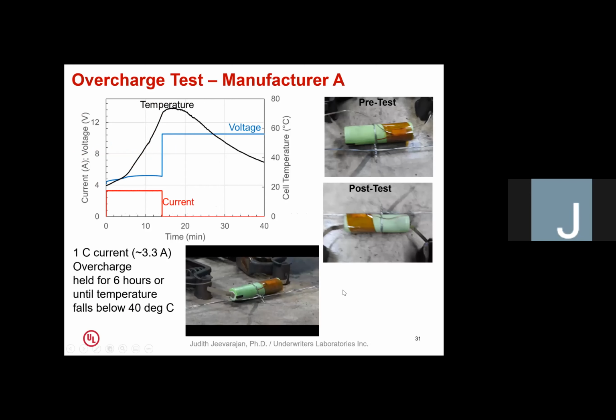So going into the overcharge test, I know this is manufacturer A. I'm going to play the video. What you'll see from this is that the CID actually activates, and even after 6 hours of holding it in an overcharge condition, nothing happens to it. It just sits there with the CID, of course, popping open, but no other reaction to the cell. And if you look at the voltage and current profiles, when the CID opens, the current falls and the voltage hits the max of the equipment.